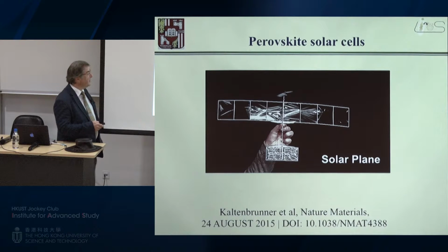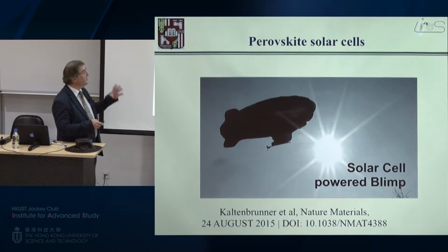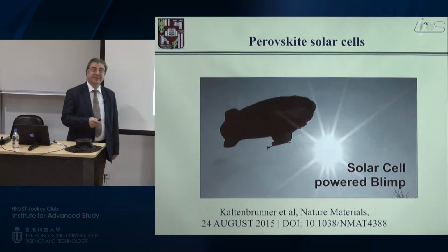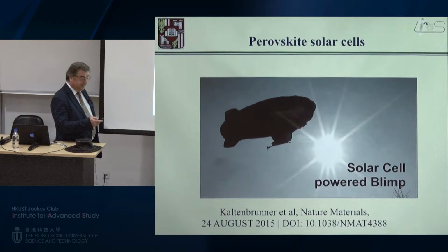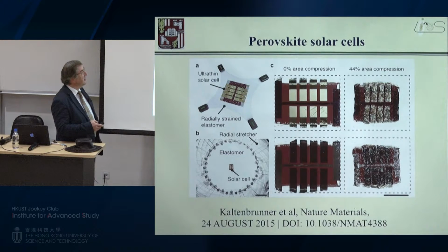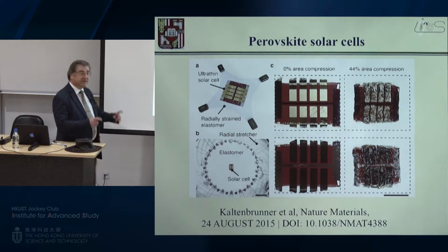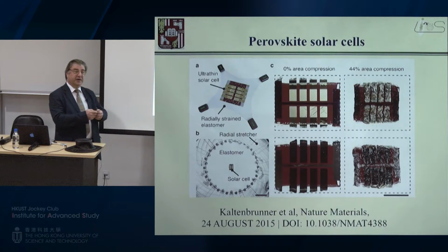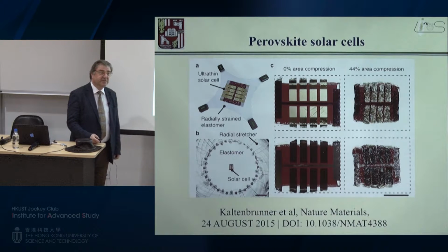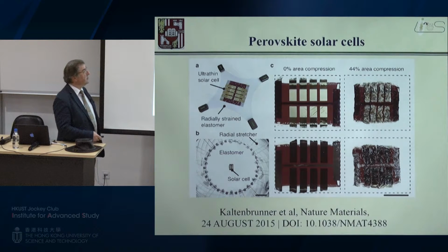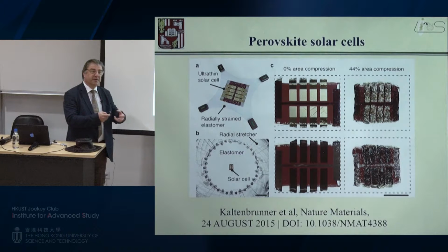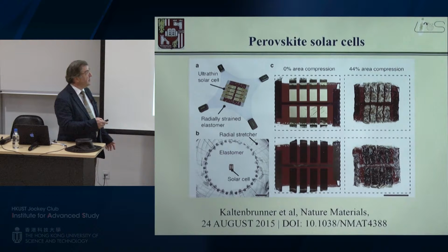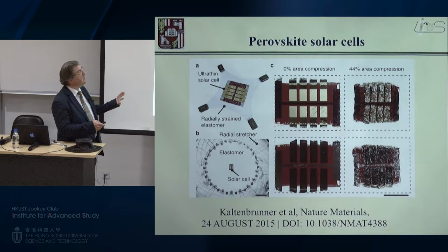This was the paper last year in Nature Materials. We made some of these zeppelins. You can fly them up quite nicely. And the interesting part, which is unexpected, is that these perovskites cast on a plastic pre-stretched elastomer foil, you can perfectly wrinkle them, perfectly deform them, and they still continue working on elastomers. So this was something which I didn't expect.